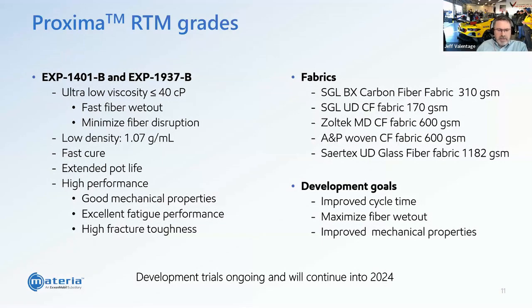Again, very low density with these grades, 1.07. And you've seen in the previous videos, we got very fast cure time and also extended pot life. Those two we can control based on the catalyst/resin system that we are putting together for a specific application. So if a customer needs some extended pot life because of the way they produce the parts, we can certainly look at that too.